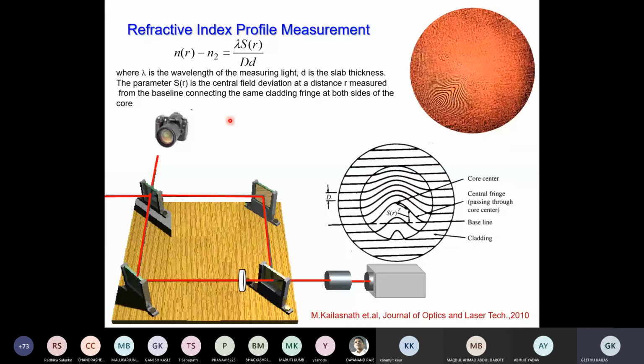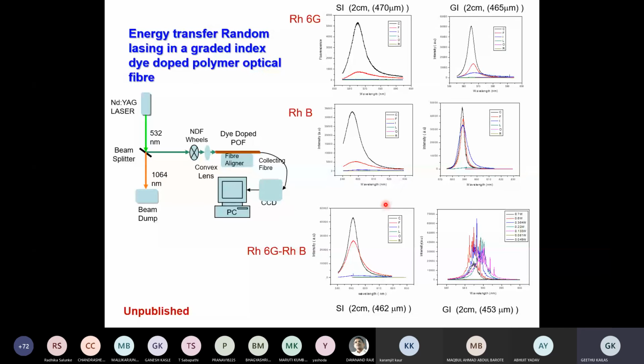Once such a graded index polymer is fabricated, it is desirable to study its refractive index profile. For that, we usually take a small cross section of the rod. It is kept in one of the arms of a Mach-Zehnder interferometer, and the interference pattern is imaged using a high quality camera, and you will find interference fringes something like this, from which you will be able to calculate the graded index structure that is actually formed in the sample. This is one interesting result that we obtained.